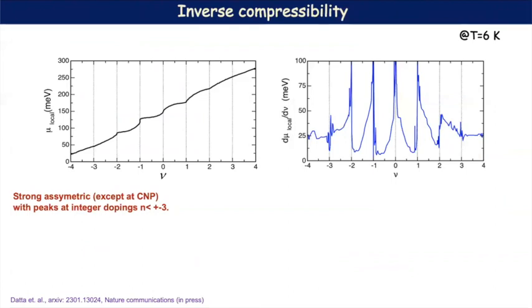Now, we also have the inverse compressibility. On the left, I have the local chemical potential, where there are small steps at integer fillings. This is the filling factor again. And on the right, I have the inverse compressibility, which is basically the derivative of this local chemical potential with respect to doping. Here you can see these strong peaks at all the integers except at plus minus 3. You can also see that except at the charge neutrality point, these peaks are strongly asymmetric, and they are asymmetric in an opposite way on the electron and hole doped sides.